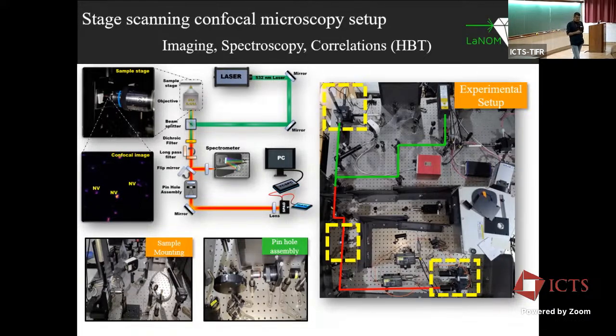What you're saying is right, but those are all simulation results. If you look at any photonic crystal cavity papers where people simulate, it shows a very high Q factor and an expected Purcell factor of hundreds. But when you do the real experiments, the change is only 5, 6. Because in experiment you have a lot of disorder in the sample, and that will kill the cavity effect.